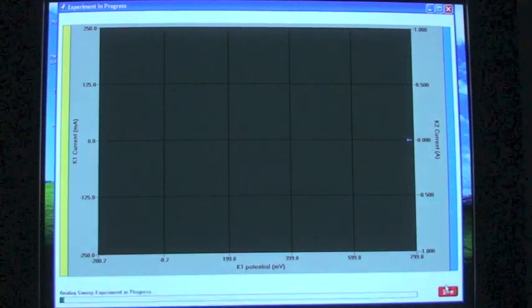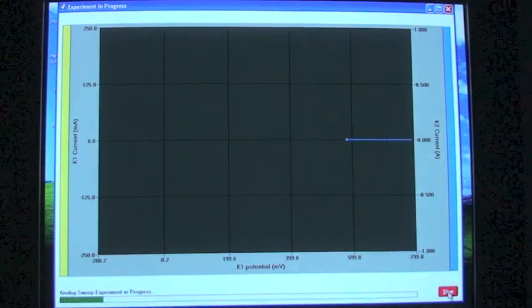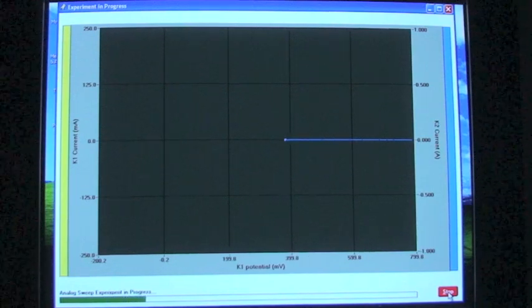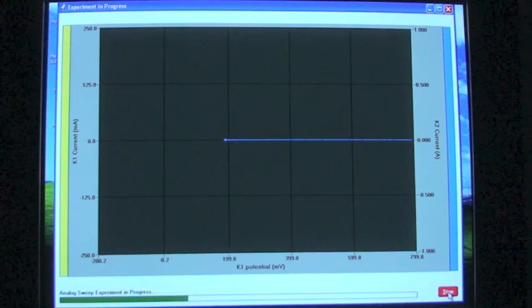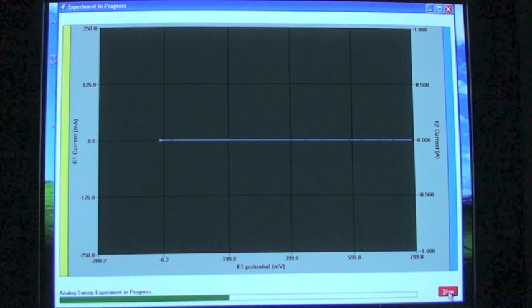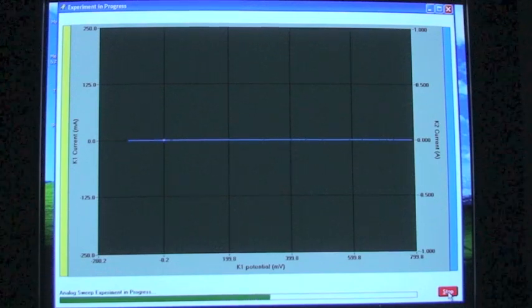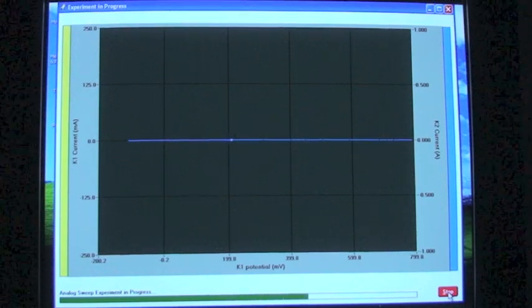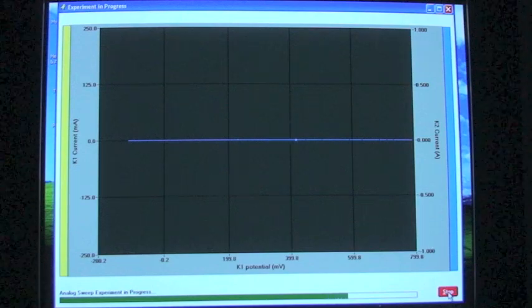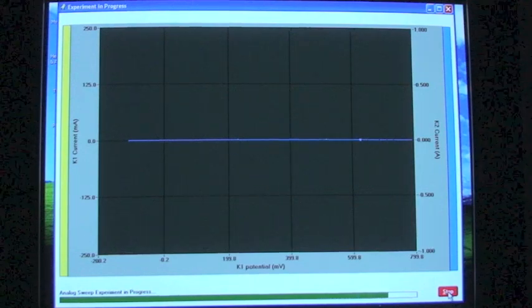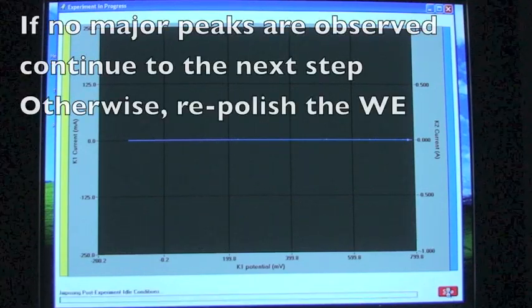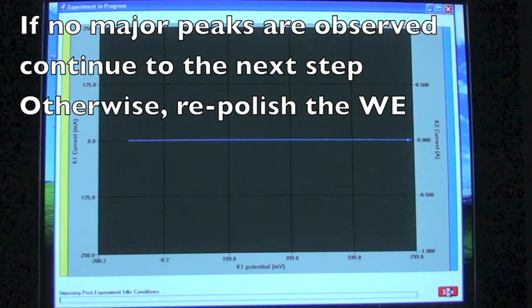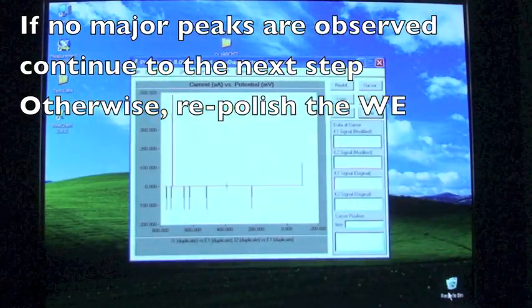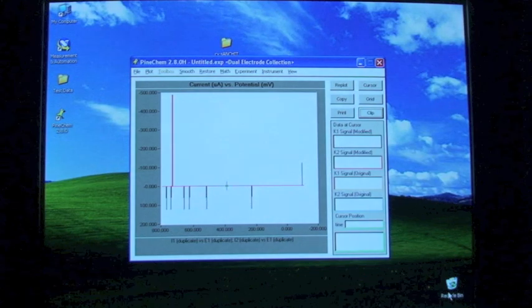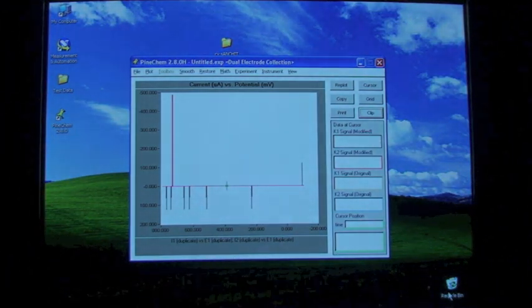The potassium nitrate solution should not have any electrochemically active species present. Thus, no significant levels of current should be passed between the working and counter electrodes until the decomposition potential of water is reached. If no major current peaks are observed, the electrode is ready for use. Some noise is expected from the sweep, as seen here. If larger currents are observed, there may be contaminants or defects on the electrode surface, requiring it to be polished again.